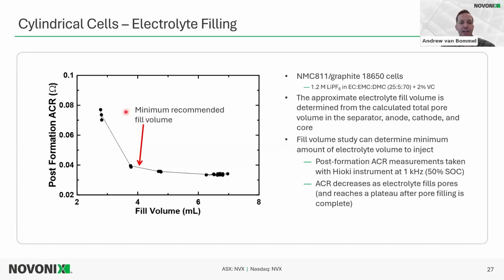And then we can adjust by going more and less than that fill volume. A good check to see if the fill volume is good is to start at a much lower fill volume and continue to make cells with higher fill volumes. We do an ACR measurement, which is done with a Hioki instrument at 1 kilohertz, after formation, at 50% SOC. If we do that post-formation ACR, we can see that resistance will decrease as the pores are completely filled, and then it will stabilize, it will flatten out.